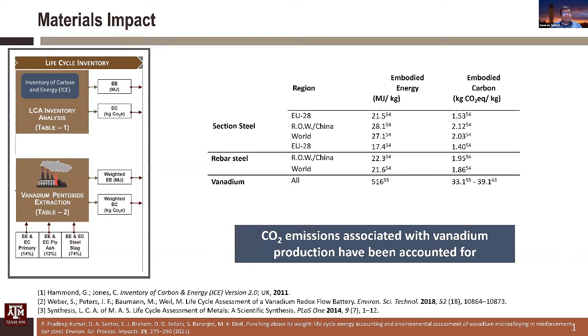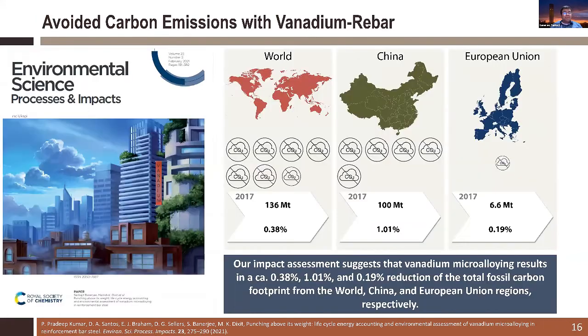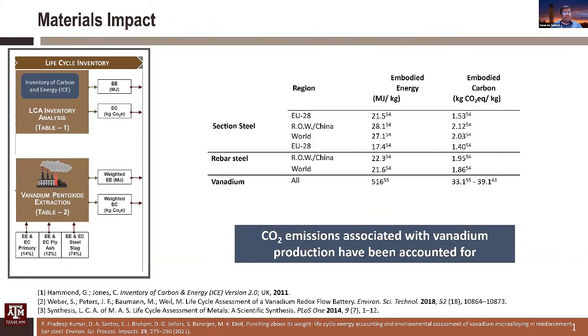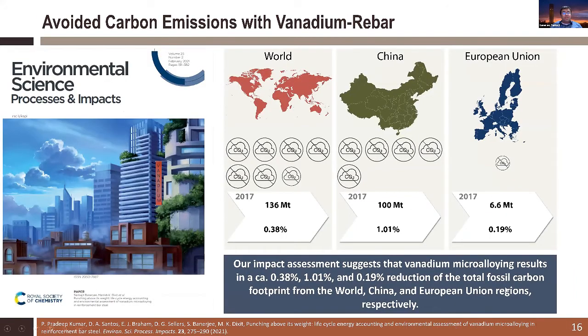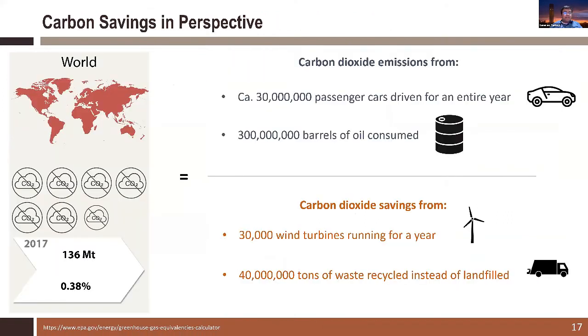And so as a result of simply rebar, if you extrapolate these numbers, and I'm going to show some specific case studies, if you extrapolate these numbers and complete this entire framework, just to be brief, we can show that vanadium microalloying, even though it's a relatively small amount, less than 1%, results in about a 0.38% global reduction in the total fossil fuel carbon footprint. And a lot of this is coming from China.